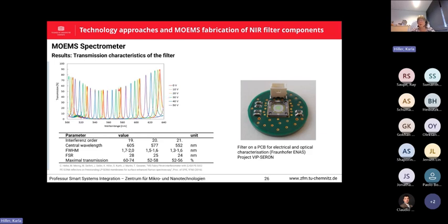Then we have the same periodic signal again. And here it's also shown it depends on the voltage which we apply. So the higher the voltage, the transmission wavelength goes down, and then it repeats for the next order, and so on and so on. So we can choose maybe this working range or this working range, and you see we have a transmission of about 50 to 70% and really a very small bandwidth, which ensures for this specific application a very high resolution.